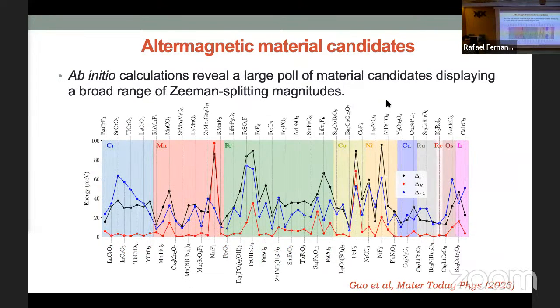Since then, many materials have been proposed as altermagnets, and some of them people in the past may have identified as altermagnets, but now you can put them in this classification. This is a very nice paper that lists a lot of materials and the size of the spin splitting. You see there's a common theme here, which I'm just going to tell you because it's hard to see: chromium, manganese, iron, cobalt. It's usually a magnetic element, if you wish, surrounded by some different local environment.